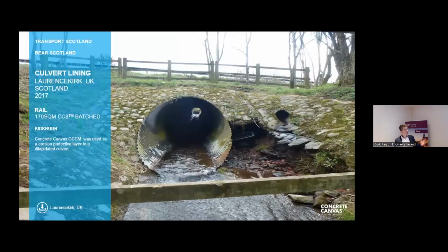And just moving into the final application, which is for culvert repair. I thought this was an interesting application to show for GCCMs, again, for existing assets, where a culvert, whether it's a masonry culvert or a steel armco culvert, that's structurally sound, was having issues with invert water loss. So you can see here in the invert, the bitumen has actually started to wear away. Due to this, a lot of the water was starting to get through the culvert invert and start to undermine the whole structure. So Transport Scotland on this particular scheme wants to prolong the design life of this structure.